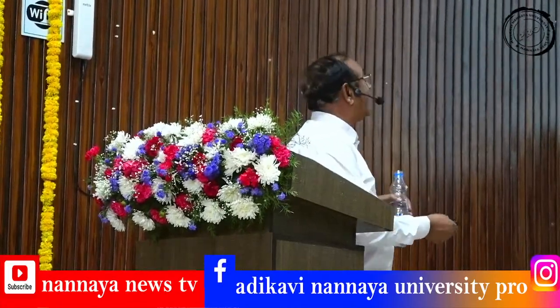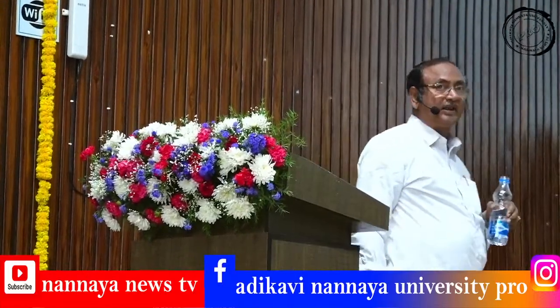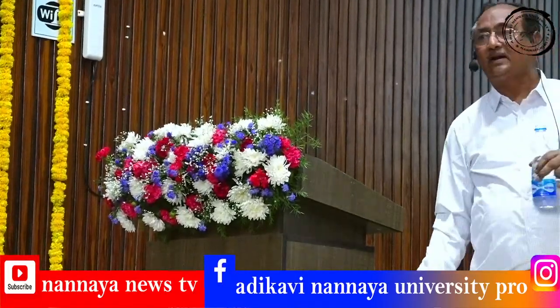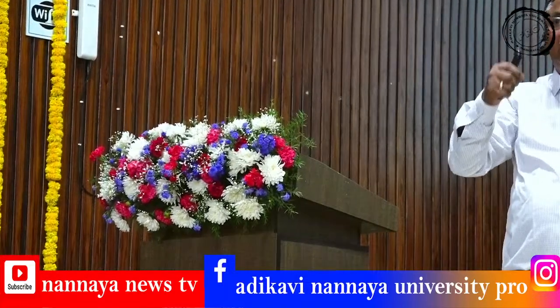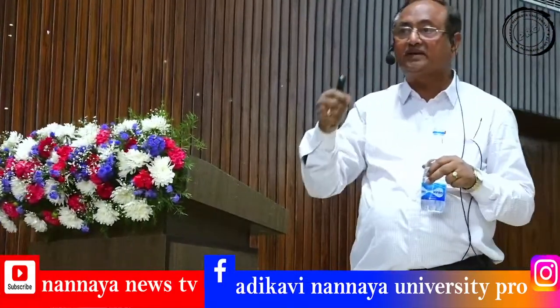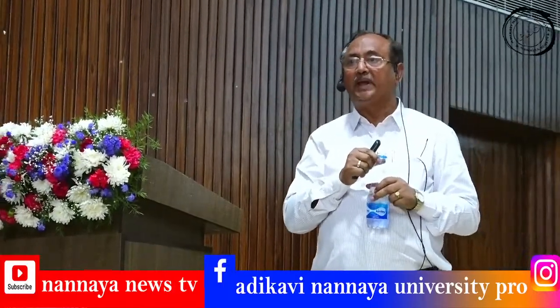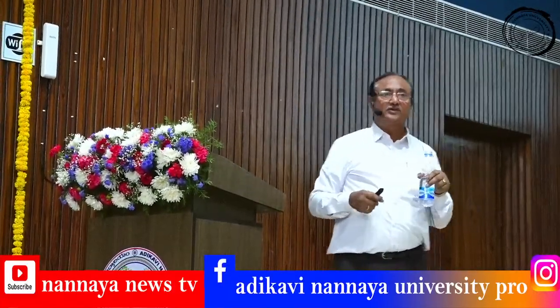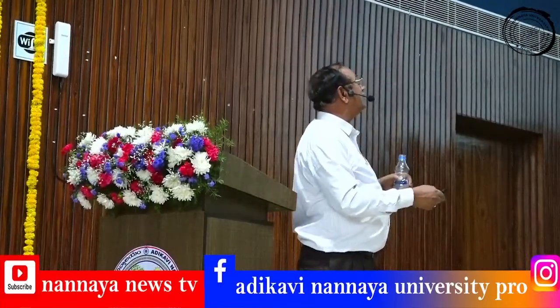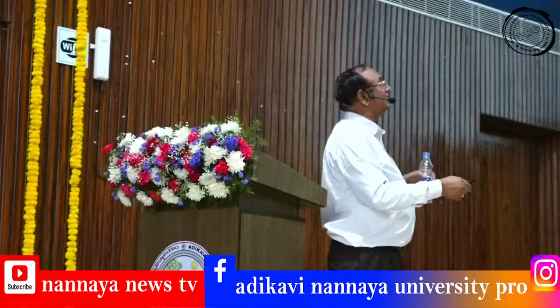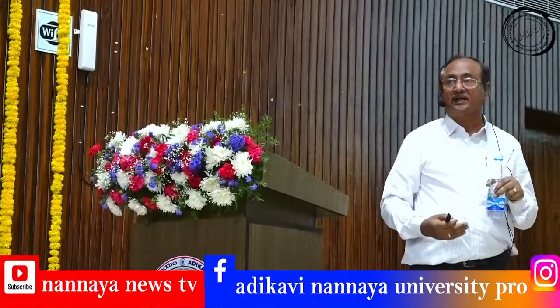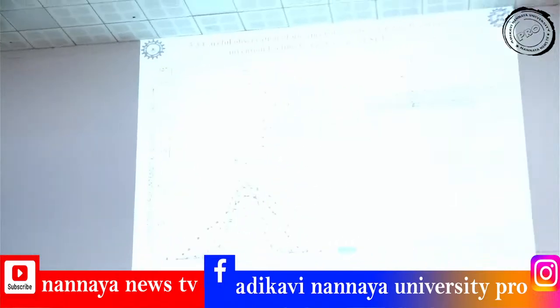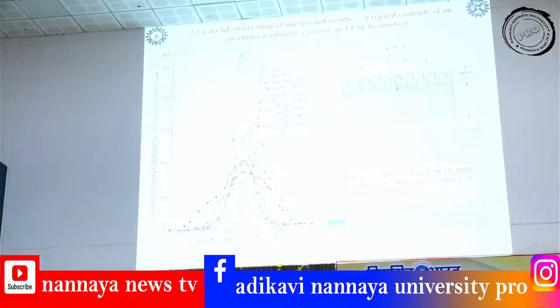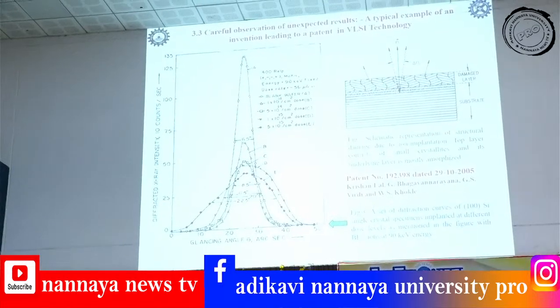This is, for example, ion implantation of various dopants. You know that ion implantation is the best method to implant the dopants at a predetermined depth. This is one of the best techniques of doping in VLSI and ULSI technology. But the thing is, while doing so, your surface will be damaged a little bit. So you have to recrystallize. There are some methods like thermal annealing, rapid thermal annealing, laser annealing and so on. But all these involve a temperature effect. So there is thermal diffusion of dopants because of the thermal nature.